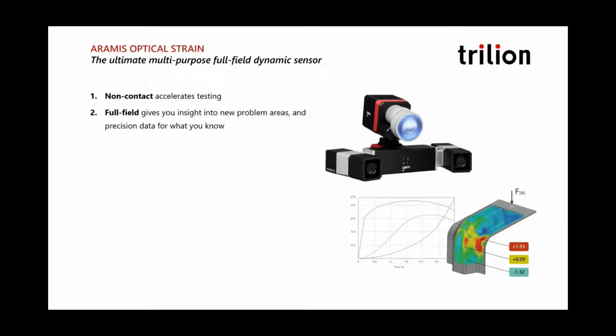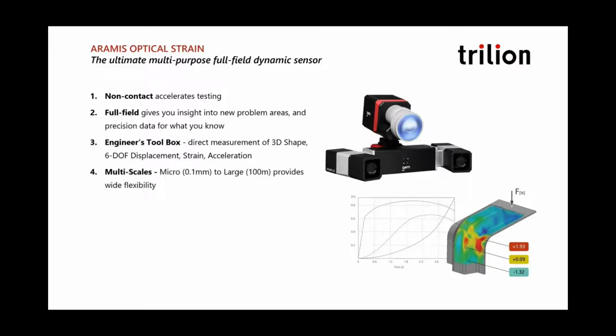It's full field, so the idea that, with a strain gauge, you need to estimate where the strains are going to happen and then put the strain gauge down. Here with full field, not only do you get the absolute strain in the right coordinates, but you also can see things that you may not have expected. We call it the engineer's toolbox because not only are you measuring strain, but you can say, well, what are the displacements that are causing these strains? What's the CAD underneath the structure that's causing the displacements that are causing the strains? You can really interrogate the results.